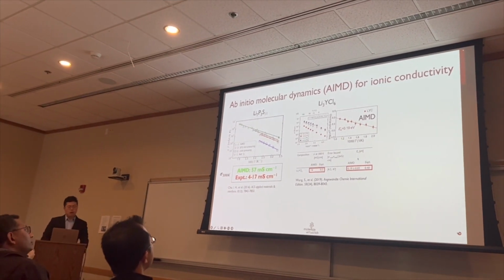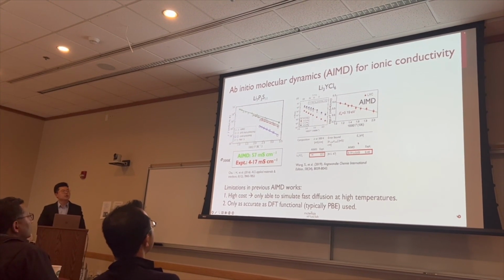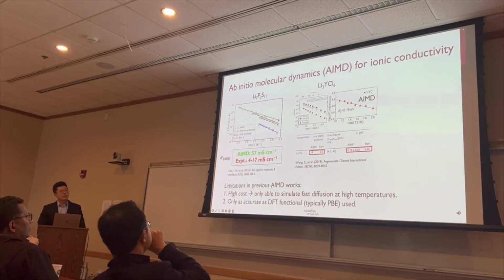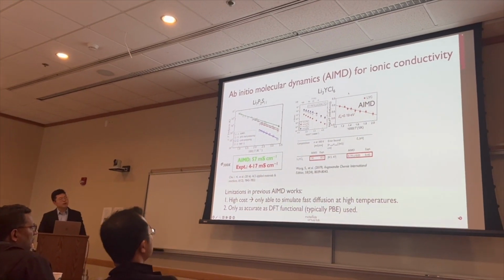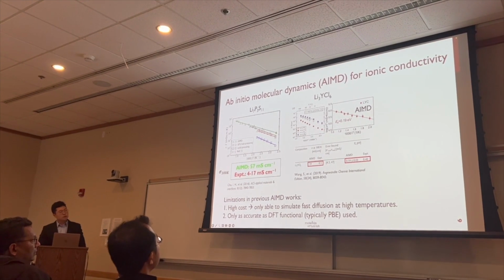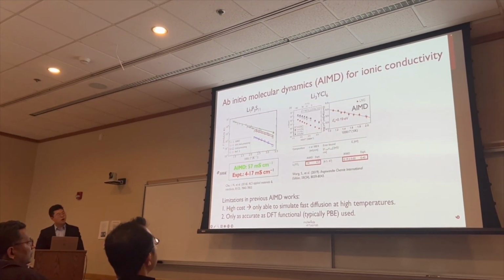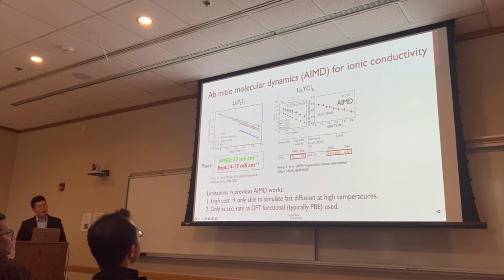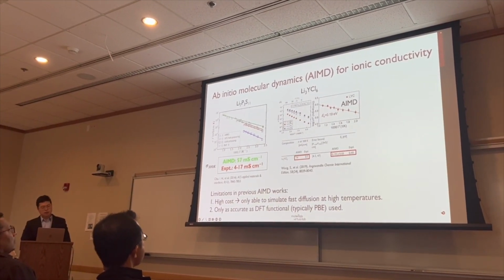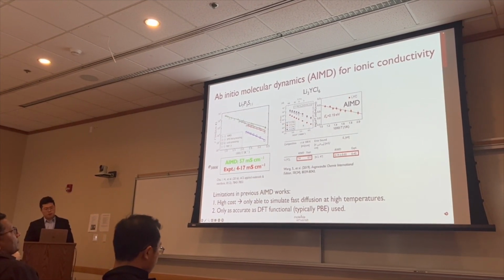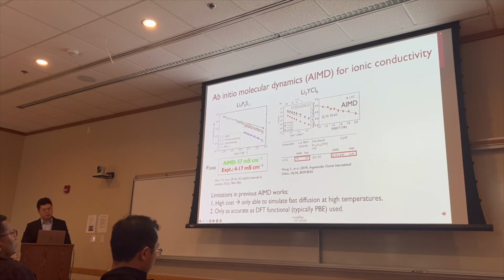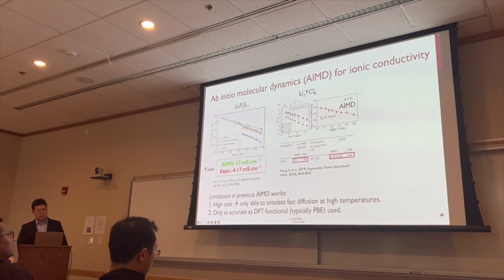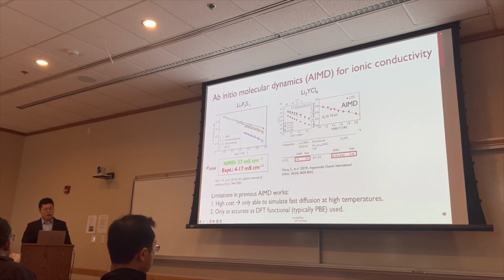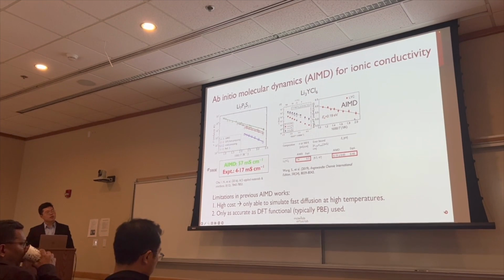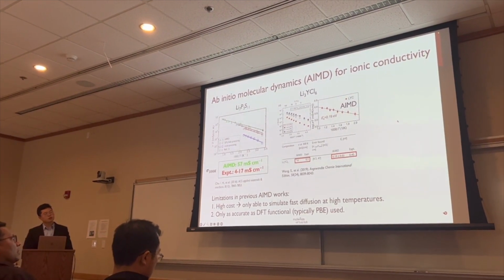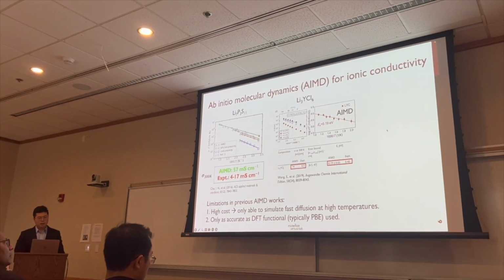We attribute this error of those AIMD results to two limitations in those previous AIMD works. The first is high computational cost. If we look at the result of the LYC system, we can see the AIMD results are all collected at temperatures at or above 500 Kelvin, while experimentally, the relevant temperature range is in the room temperature regime, below 400 Kelvin. This is the same trend in the LPS system. This is because AIMD is so expensive that we're only able to simulate fast diffusion at high temperature, and then we assume the activation energy is constant. Then we extrapolate down to room temperature to get the diffusivity and ionic conductivity at room temperature.